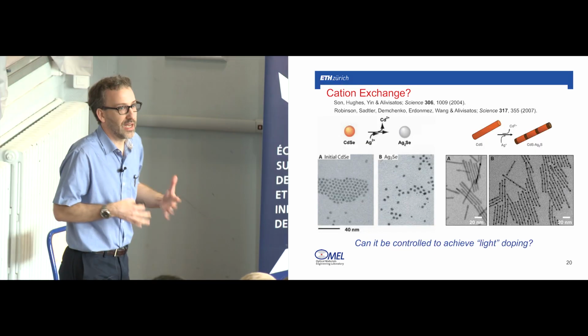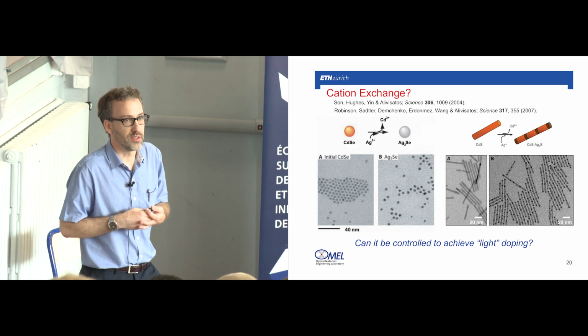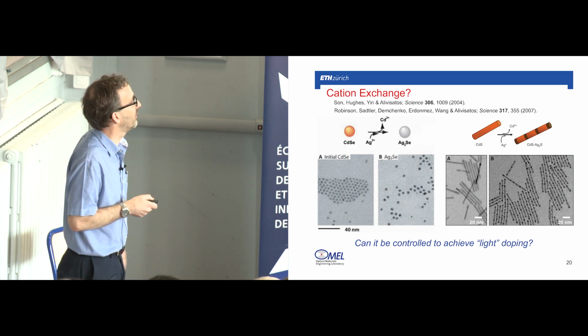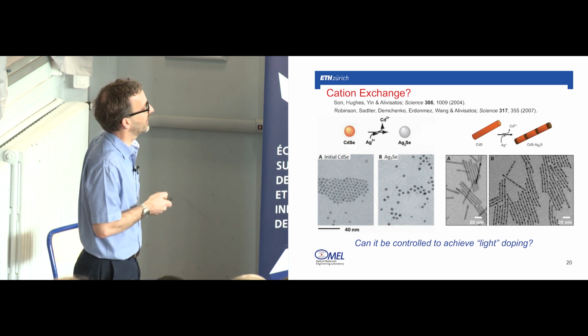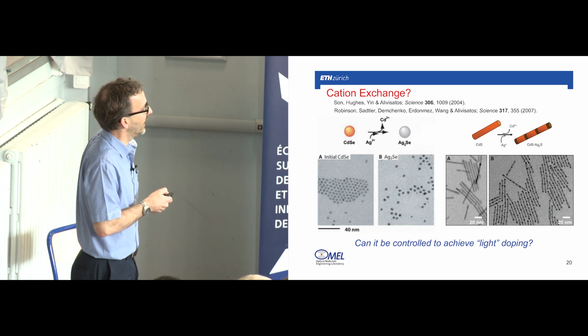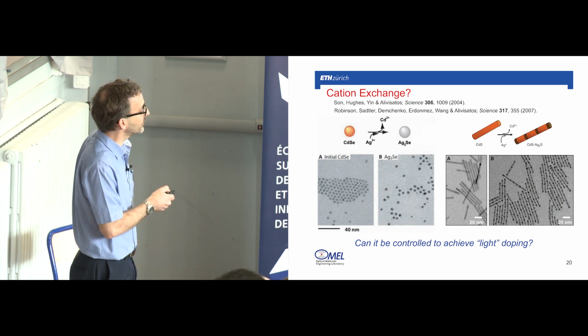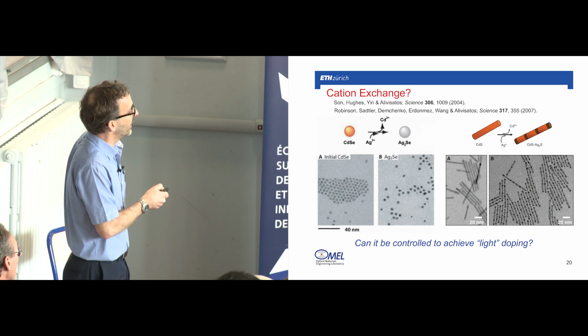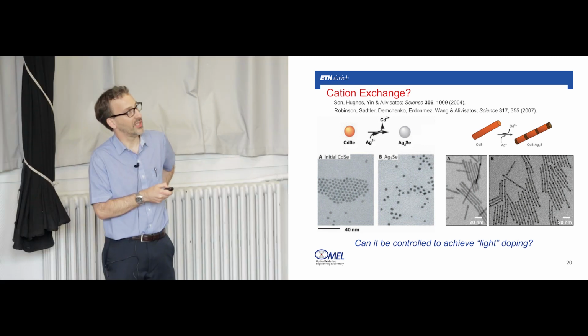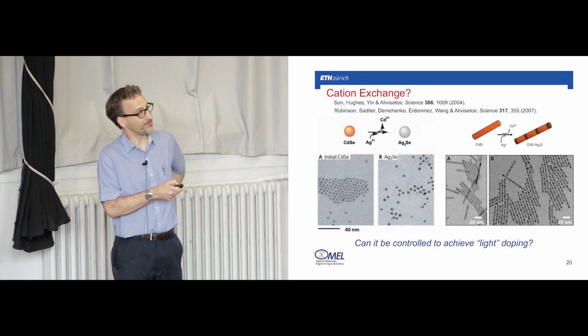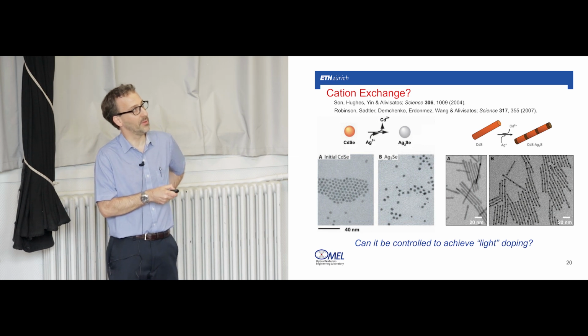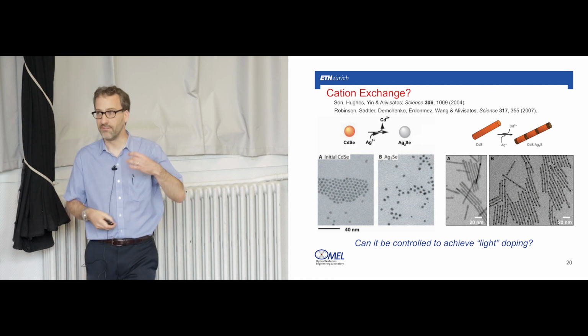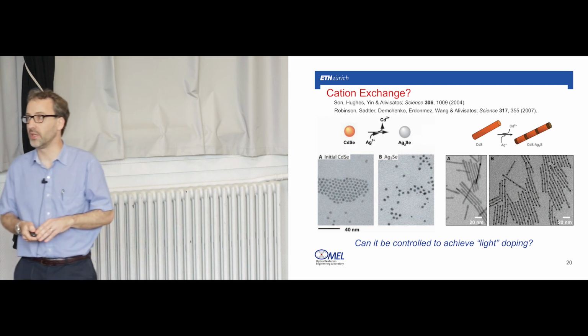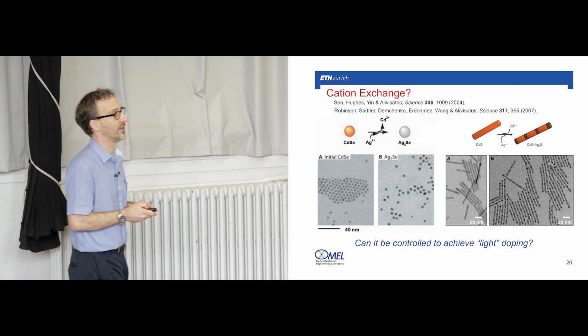So then the question is, how are you going to incorporate the impurities? And to avoid all these kinetic problems, we started looking at this process of cation exchange to do the doping. We heard yesterday from Rahman about this idea of cation exchange that was introduced by the Alivisatos group, where if you take cadmium selenide nanocrystals and expose them to some silver cations in solution, they very rapidly completely convert to Ag2Se, so silver selenide.